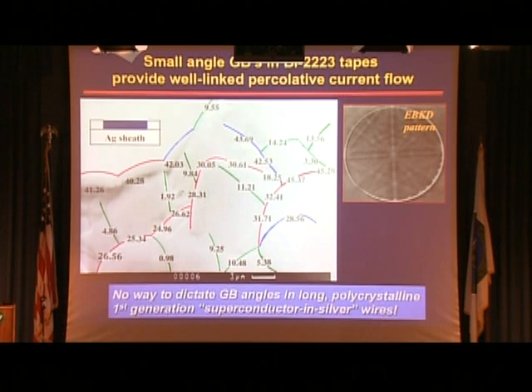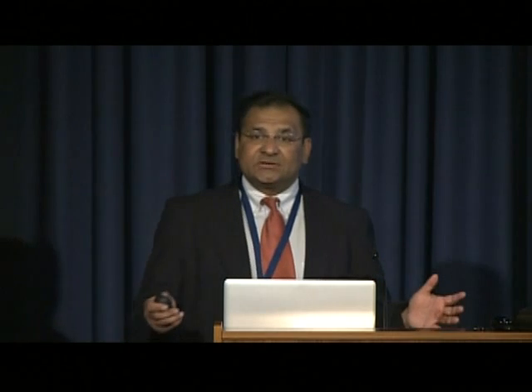And what we found was that one could trace percolative paths through green boundaries, which are low-angle boundaries, through much of the material. But in order to improve the performance of a kilometer-long wire, it would be impossible to dictate that process to align, for all the grain boundaries to align. So in the superconductor and silver model, it would be very difficult to get higher performance.